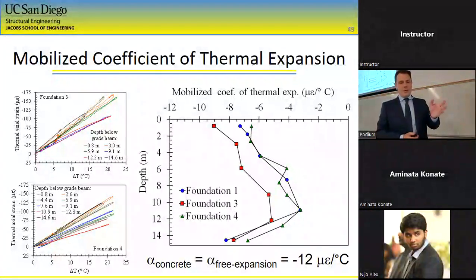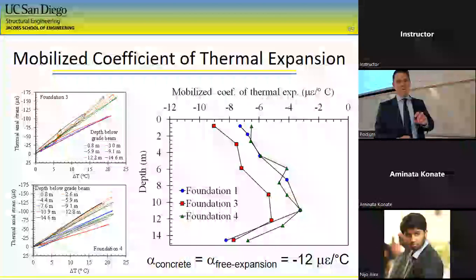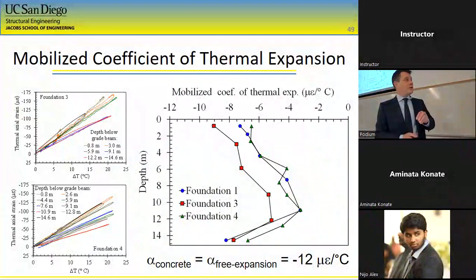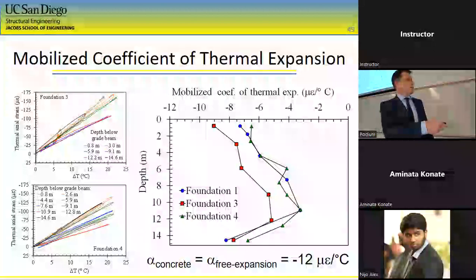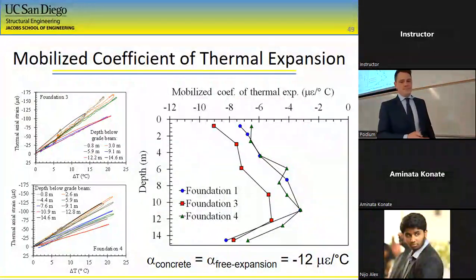We'd expect from an end-bearing pile with friction that the smallest strain would be at the base and that you would have no mobilized coefficient of thermal expansion. You would prevent it from moving. But actually, it was pretty high at the base, and that was why we thought that we had loose sand down there. You could just compress that loose sand, and it's able to expand. So our null point was at the location where the mobilized coefficient of thermal expansion was the smallest.